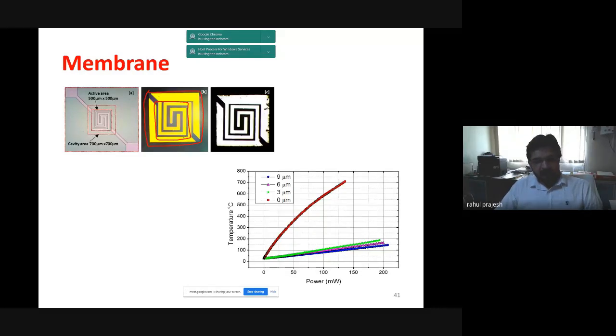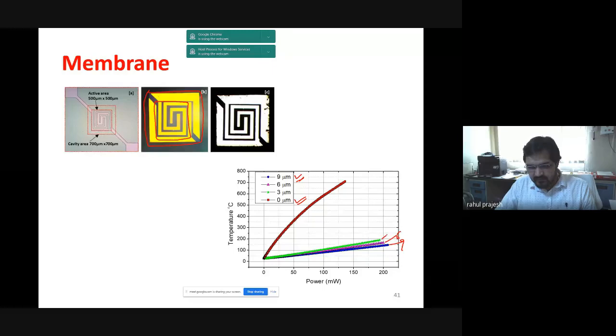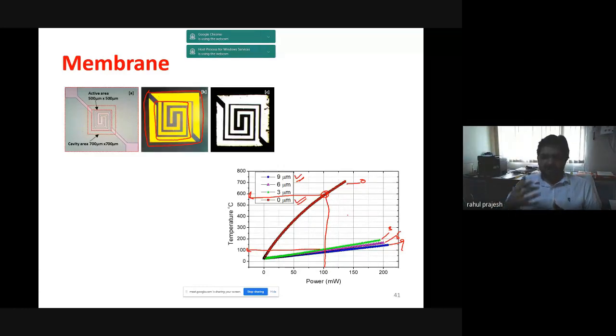It's also important how much material you are removing from the back. Either you are removing the complete silicon from the back, or there is some silicon left at the back. So these are the results. This is 9 micron silicon left, this is 6 micron, this is 3 micron, and this is 0 micron, that means no silicon left. You see the drastic change in temperature increase. At 100 milliwatt you are able to achieve 600 degrees centigrade. But if silicon is remaining on the back, you are only able to achieve 100 degrees centigrade. So this is the advantage of having removed complete silicon from the back. Your complete silicon from the back should be removed to achieve the best performance of your sensor.